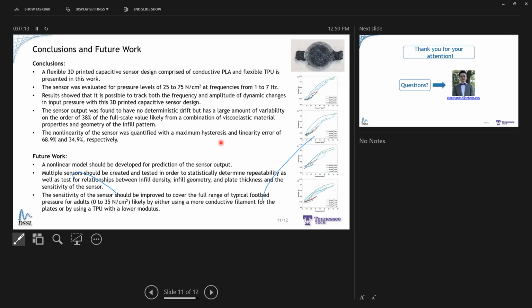So overall for this project, we were able to create the flexible conductive PLA and TPU capacitor sensors and evaluate them at pressure levels between 25 and 75 Newton per centimeter squared and frequencies from 1 to 7 hertz, and found that they were able to track these dynamic changes in pressure with no deterministic drift. But we did see a high amount of variability on the order of 38% and a high amount of nonlinearity with hysteresis on the order of 68.9 and linearity error 34.9%.